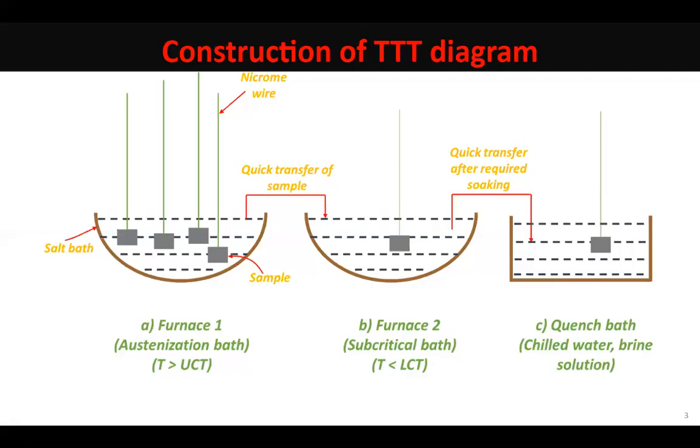But here, for your understanding, you just need to remember that if austenite phase is present in the steel and the steel is quenched, whatever austenite was present will transform only into martensite. It will have no other option. So where does our interest lie? As I said a while ago, our interest lies in the non-martensitic phases that would be seen in the sample that has been quenched and brought over here, because that would give you an idea, for a given transformation temperature and the time spent at that transformation temperature, how much of austenite had transformed and into what phase.